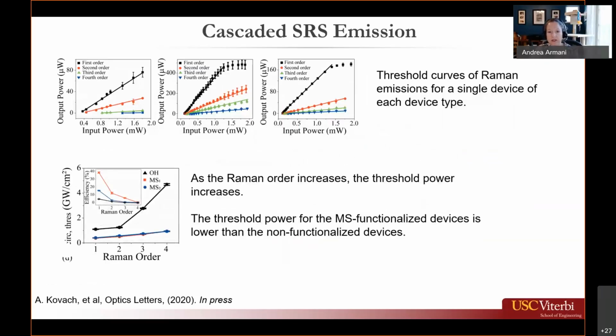So when we look at the cascaded emission in a little more depth, and we take threshold curves of each one of those cascades individually, so first order, second order, third and fourth order, for both silica devices as well as the functionalized devices. As the Raman order increases, the threshold power required for the silica devices, which is this black line in the bottom, significantly increases. It starts off at a higher power as well as increases at a much faster rate. In contrast, the threshold power required as well as the rate at which it increases is significantly lower for the functionalized devices. And then the efficiency is much higher for both of the methyl groups as compared to the silica surface. So basically, it's mirroring the same behavior that we saw with just a single Raman peak.